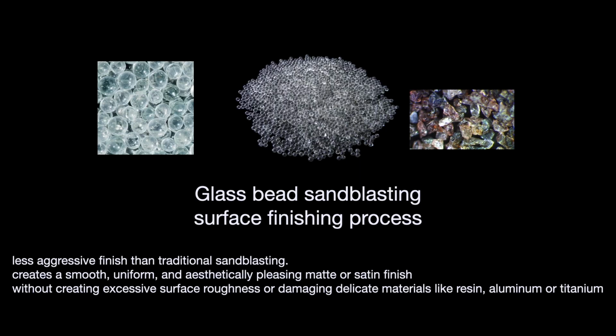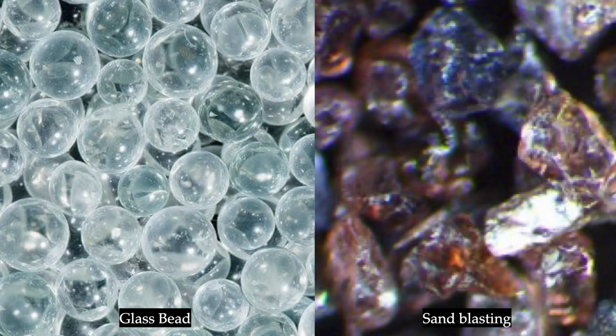It gave us a very clean surface. At the same time, it didn't remove any layers, or only a very minimal layer of material. It also makes a surface enhancement for the superficial layer of the material. So glass beads is the best. You can see the comparison between the glass beads particles, which are spherical and not sharp like the sandblasting aluminum oxide material.